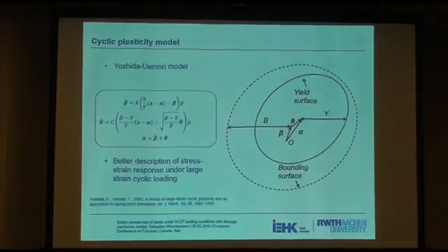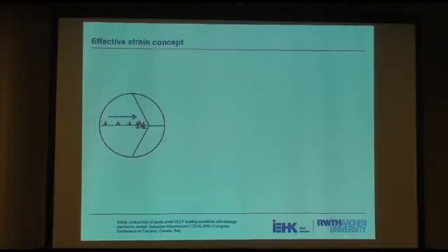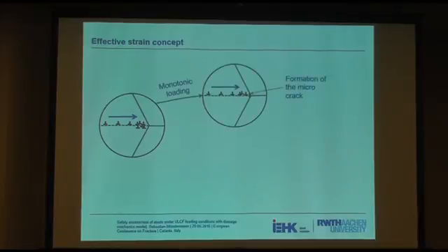component. For the cyclic plasticity model, we have made use of an existing kinematic hardening law. It's the so-called, I hope I pronounced it correctly, Yoshida-Uemori model, which makes use of two yield surfaces. Both, in our case, are only described by kinematic hardening. Usually there's also the possibility to have isotropic hardening for the bounding surface, but we did not make use of this.